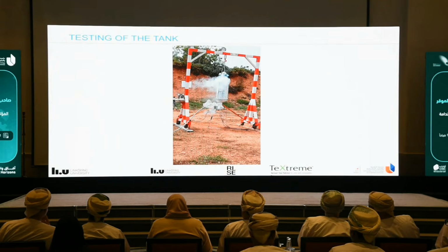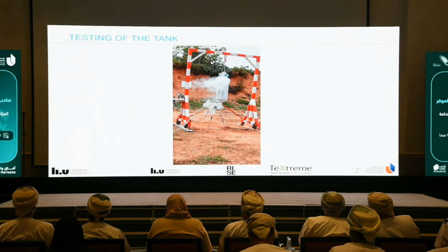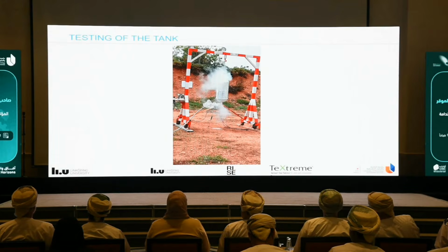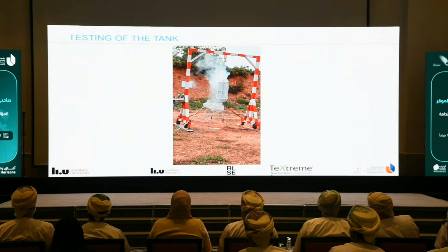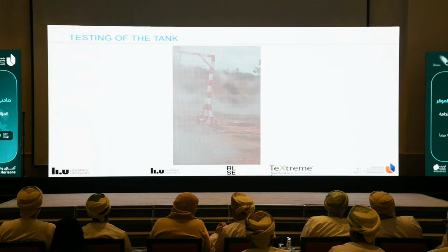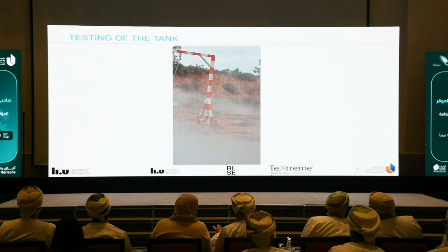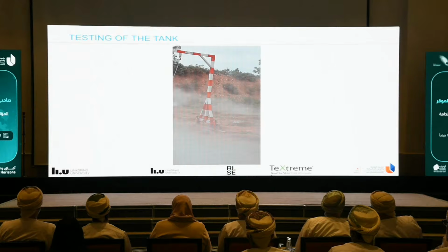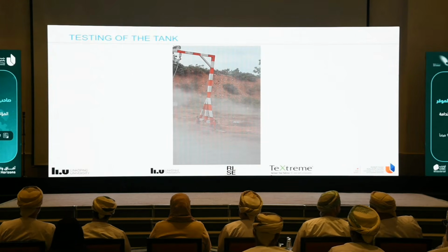And we have tested the tank. We did this outside the lab, almost in the forest, in a very safe place. And we controlled the pressure. Here we applied liquid nitrogen, and we were measuring the pressure. And we succeeded in using this material at about 50% higher than the pressure that the company wanted. So with that, we proved that this material can be used to make those tanks. And now this company, TeXtreme, is in contact with companies like Airbus, for example, who are interested in building this type of tank for their airplanes.